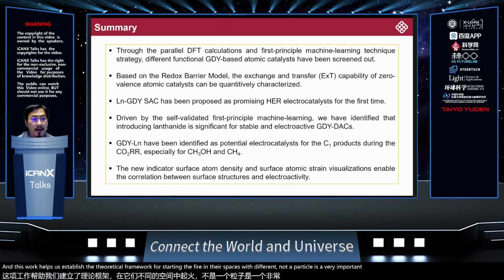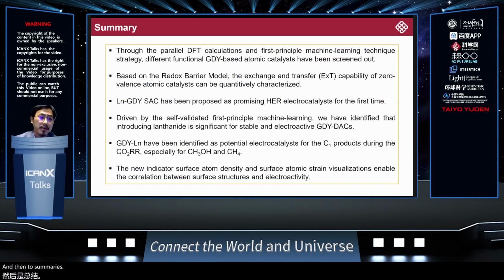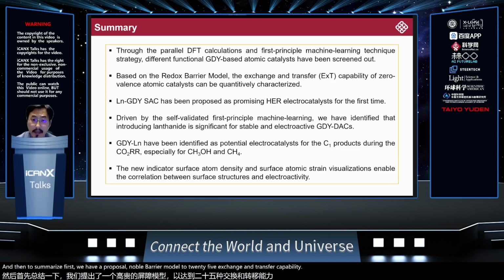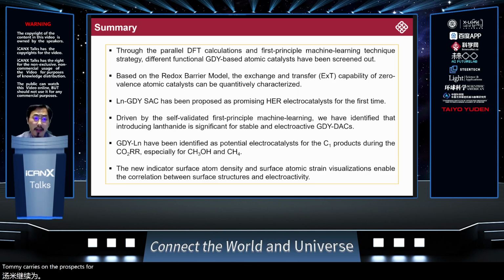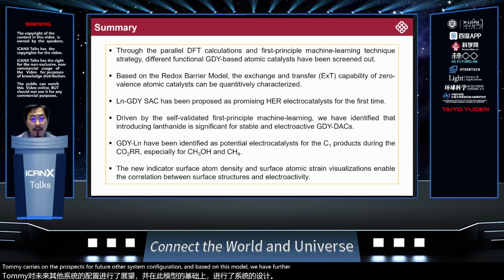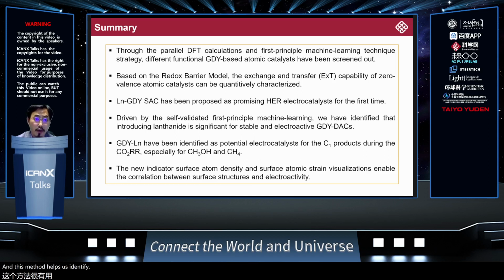And then to summarize, first, we have proposed a novel redox barrier model to quantify the exchange and transfer capability for zero valence atomic catalysts on graphdiyne, for future consideration of other systems. And based on this model, we further established the first principle machine learning method. And this method helped us identify suitable metal pairs for future dual atomic catalysts and triple atomic catalysts.